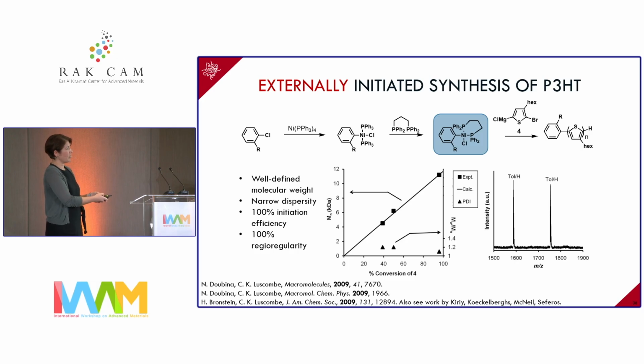There are other things like molecular weight dispersity. A dispersity of 1 would be perfect. In our case, we get 1.1, 1.2, which is good from a polymer synthesis point of view. But there are other aspects too. We're able to get 100% initiation efficiency. What that means is that every single chain has this end group on it. And there are other things like, as I mentioned, defects in polymers. We're able to make what's called 100% regioregular, in other words, 0% defect materials using the synthesis that we've developed. So the synthesis works great.